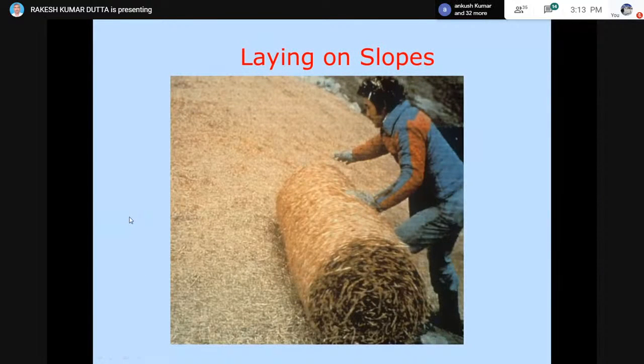So I have included this picture just to show you that when we use them on slopes for erosion control application, we simply unroll the roll in the downward direction. So things will go automatically. Then you have to bury them into ditches at the bottom as well as at the top. And in the central portion, we just drive wooden pegs at different spacing along the slope, so that the entire thing may not slide down.